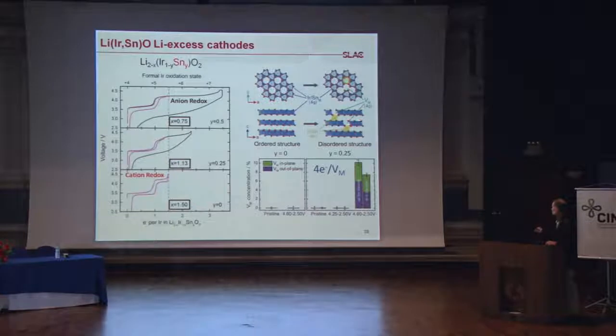So there's this type, which is if I'm a transition metal here, I jump down to the layer beneath it. But if you look here, those also can be disordering by this transition metal moving into there. And that can also give rise to disorder, the formation of vacancies. If this transition metal moves there, you're going to leave a vacancy behind here.